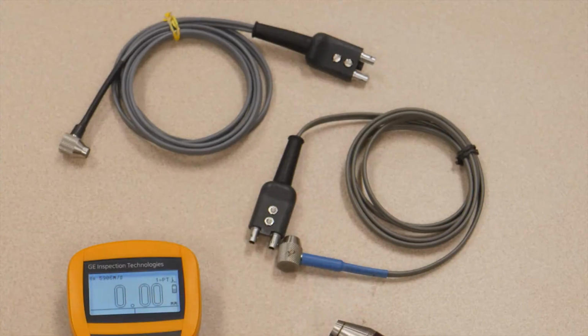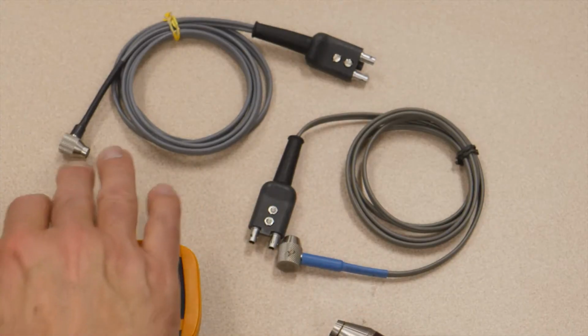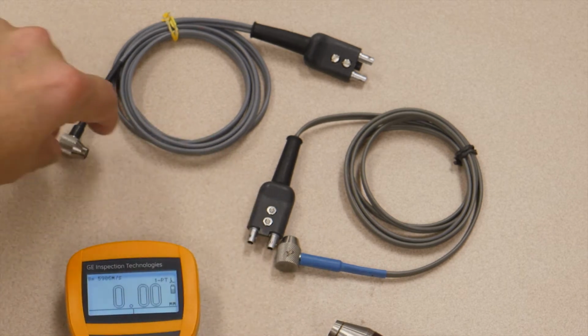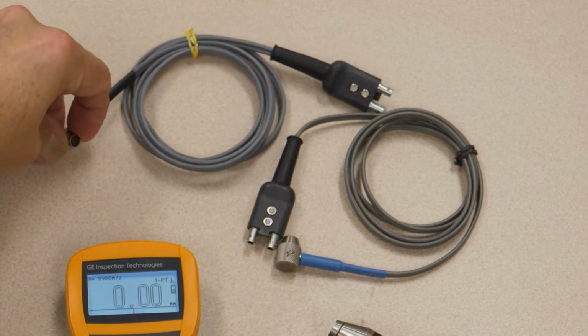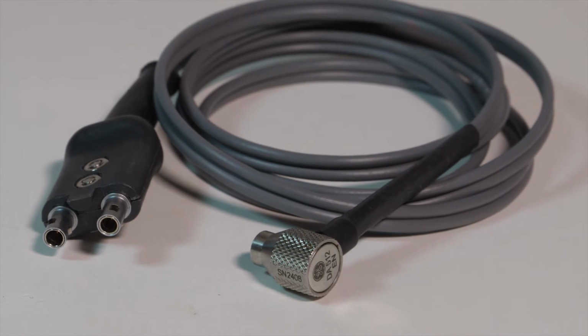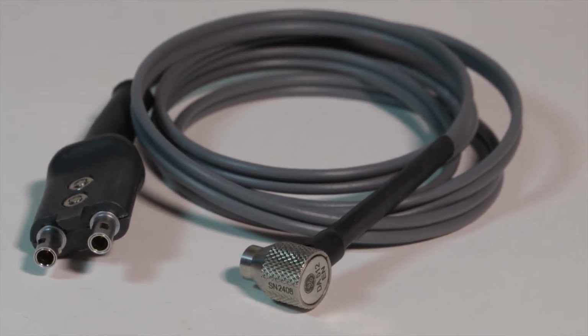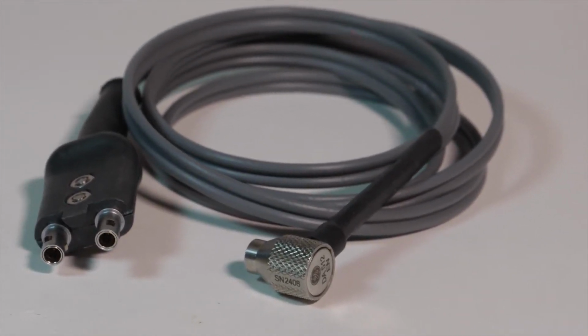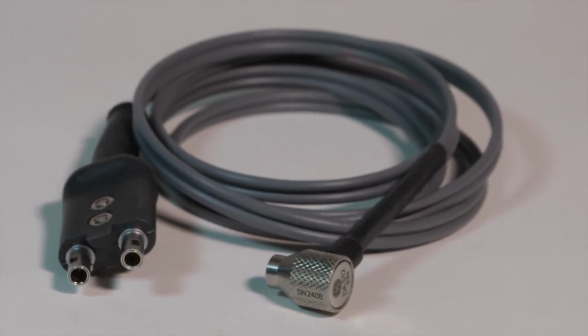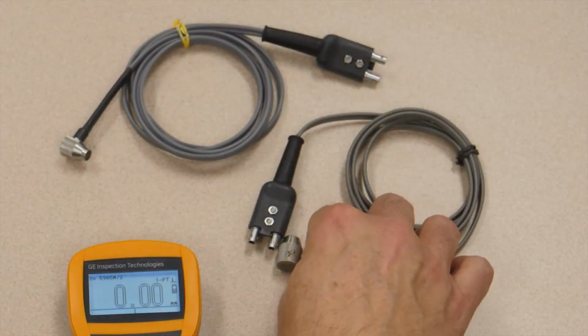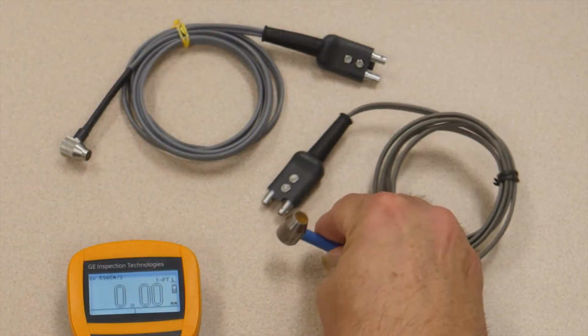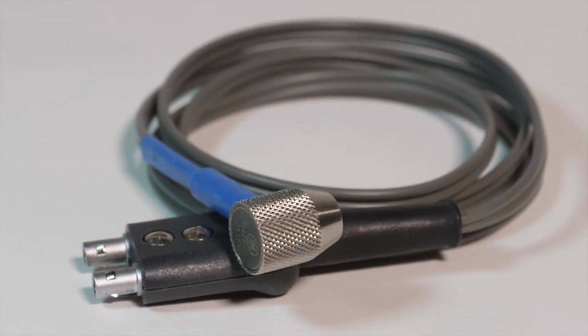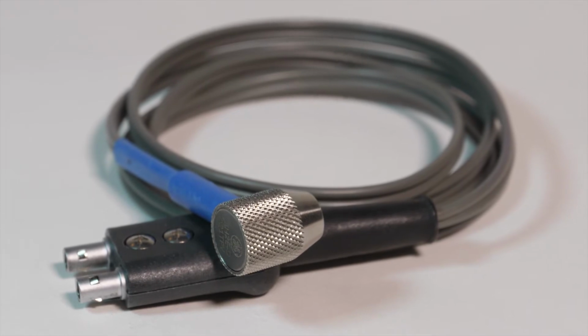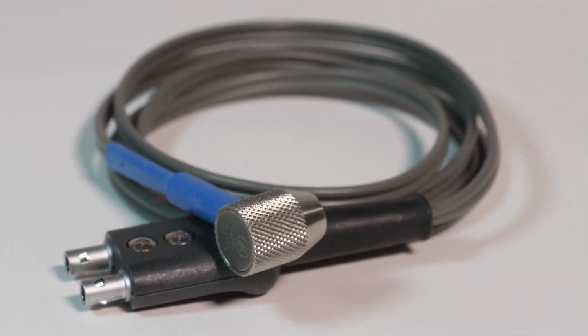And we have our fingertip probes that are commonly used. The DA512 has a very small contact area, ideal for reaching into tight spaces, ideal for reaching into pits on the surface of materials to take measurements of remaining wall thickness. Another common fingertip probe is the FH2E, a little bit bigger contact area, a little more versatile. You can work with thicker materials easily with that.